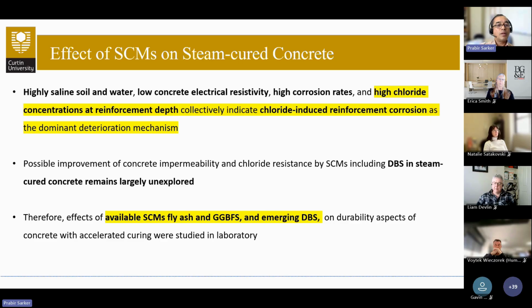One way was to look at the effect of supplementary cementitious materials on steam cured concrete. We know there's a lot of literature available on the effect of SCMs like fly ash, GGBFS, silica fume, and other types of SCMs on normally cured concrete, but there was less literature on the effect of these SCMs on steam cured concrete, or concrete subjected to accelerated curing, which is precast concrete.